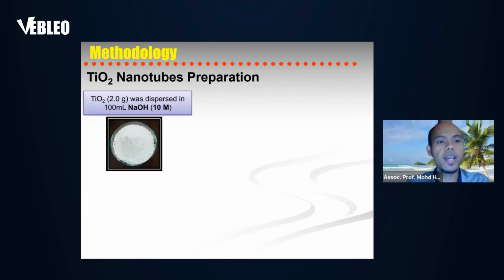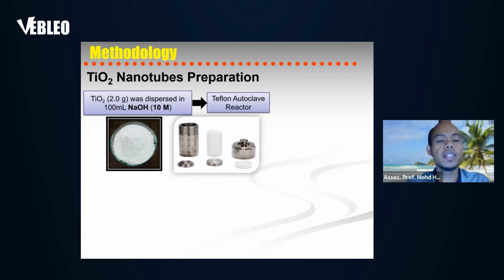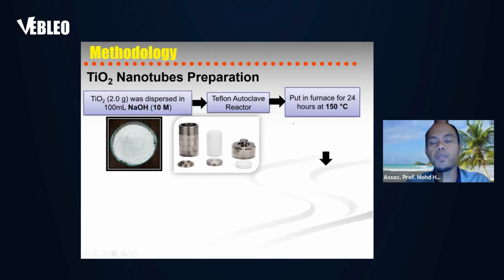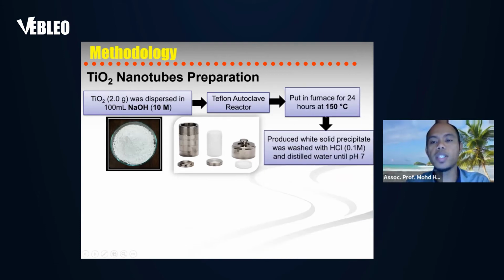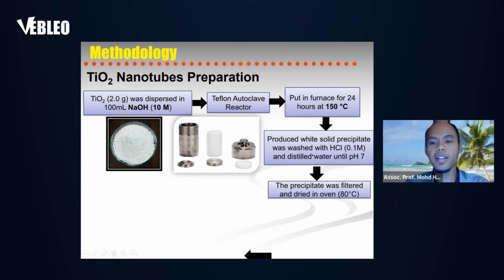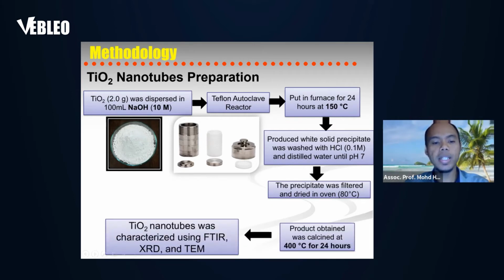So how do we prepare the 1D titanium dioxide nanomaterial? For the first step, we take commercial titanium dioxide particles and put them in an autoclave. We put it in the furnace for 24 hours at 150 degrees C. We wash it and then collect the sample. After that, we calcine the sample to produce titanium dioxide nanotubes.